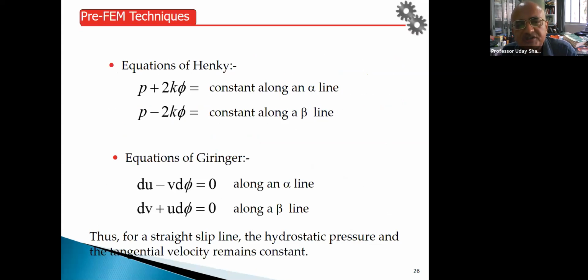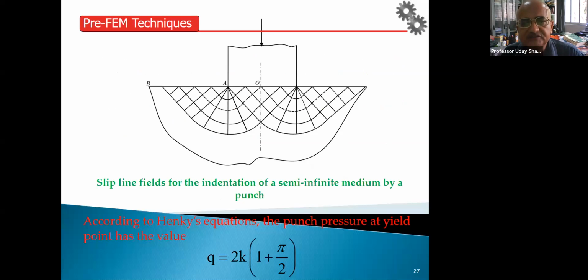We have some equations, that is Hencky's equation, that is P plus 2K phi is equal to constant along alpha line, P minus 2K phi is constant along beta line. That means if the slip line is turning, then the pressure will be changing, and similarly we can find out the velocity. So typically, say for example, you are doing the punch problem, you can construct the slip line.